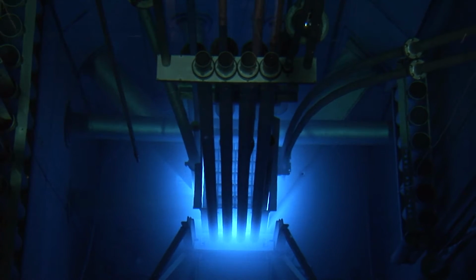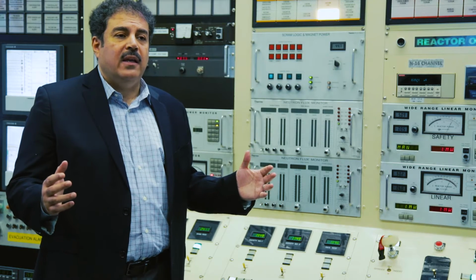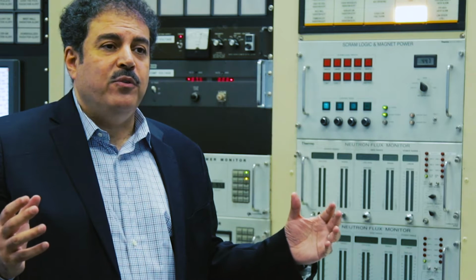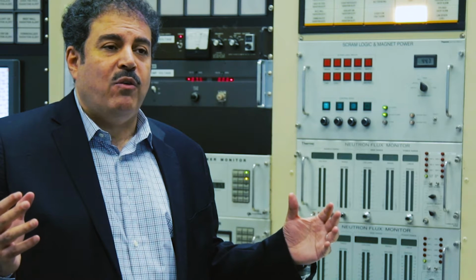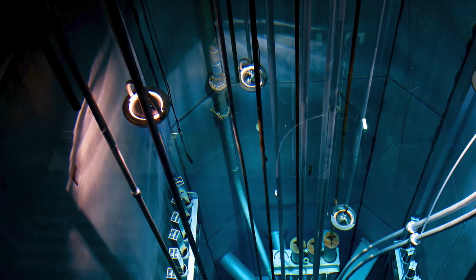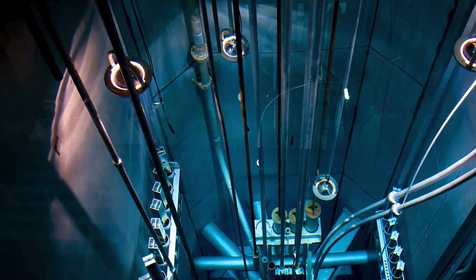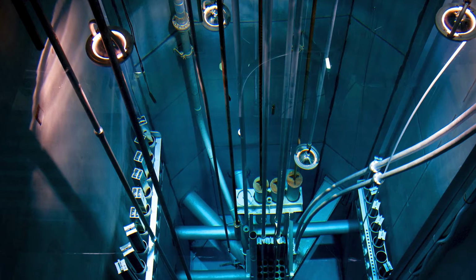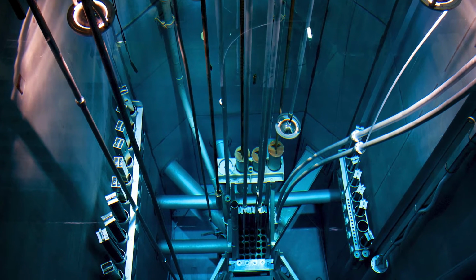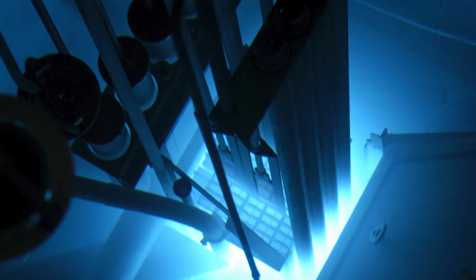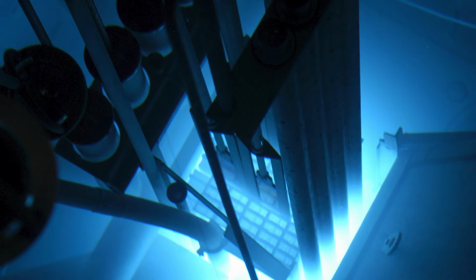The reactor itself is somewhat unique in that the moderator to fuel ratio of this reactor is almost 1, which really gives us a neutron environment where the thermal neutrons actually peak on the edges of the core, facilitating the type of utilization that we do in the PULSTAR.